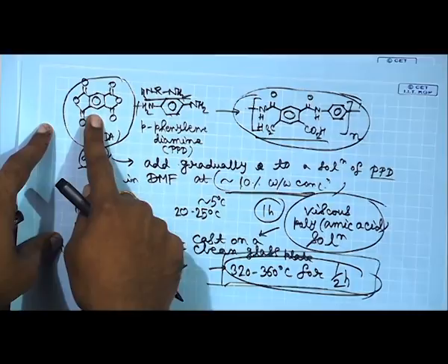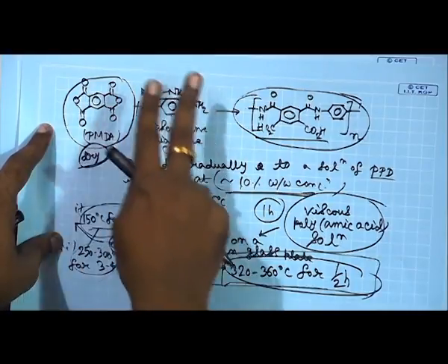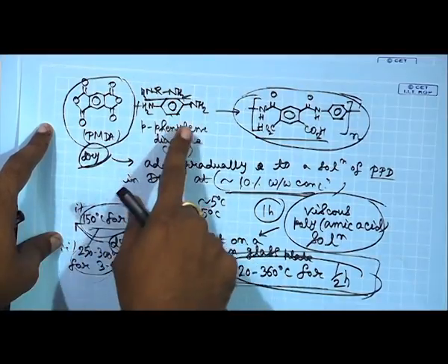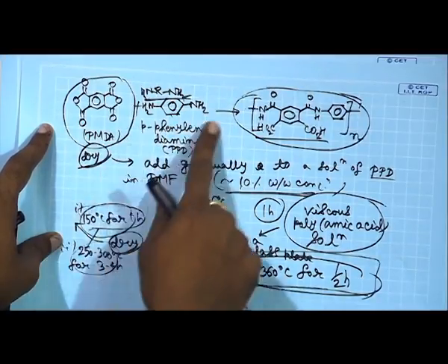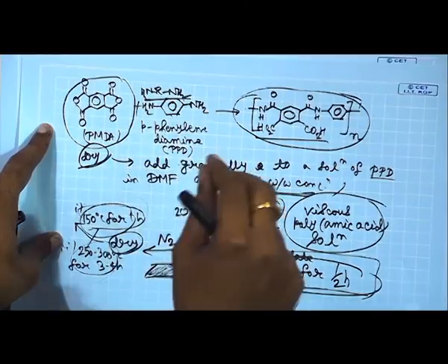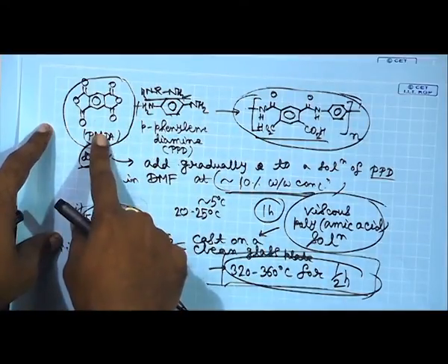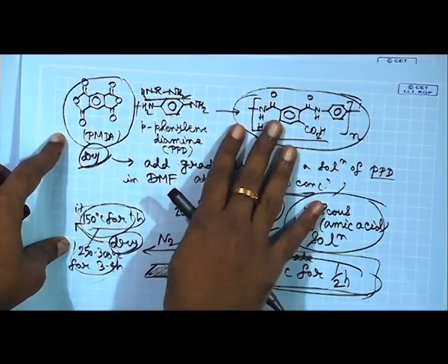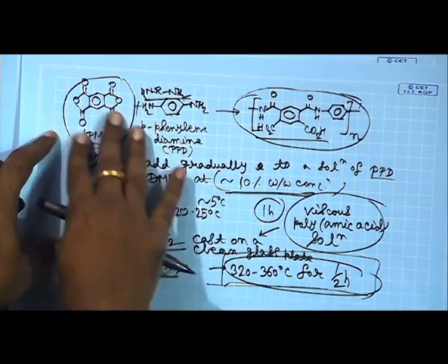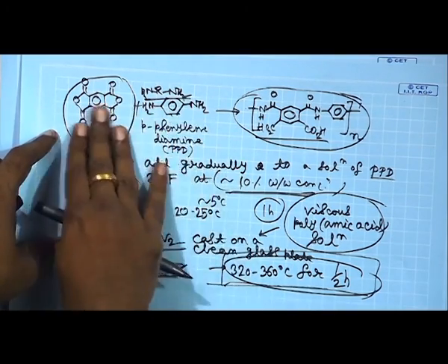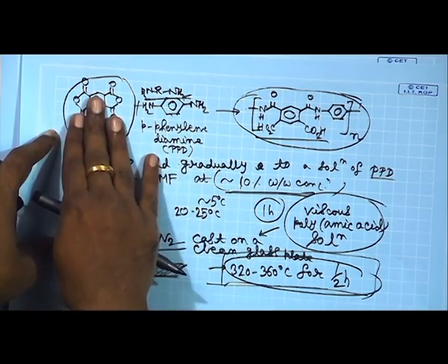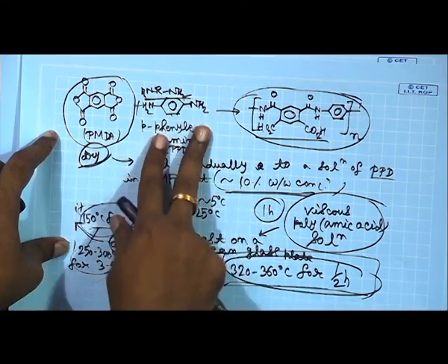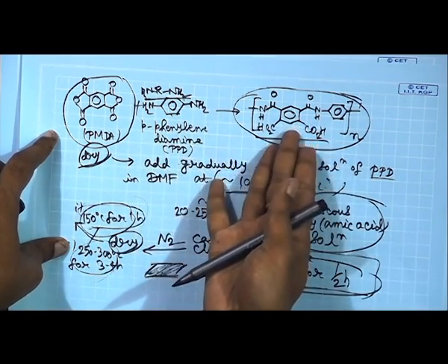So, if you add the dianhydride to a solution of diamine, at any point of time you have a large amount of diamine present and you are adding only a small amount of pyromellitic dianhydride. So, you can minimize competing reactions like the reaction with water, because before it can react with water, it can immediately react with the diamine. This reaction is faster and the dianhydride amount is already lower, because you are adding gradually to a solution of diamine. This is one thing, and of course, the solvent that you are using has to be dry.